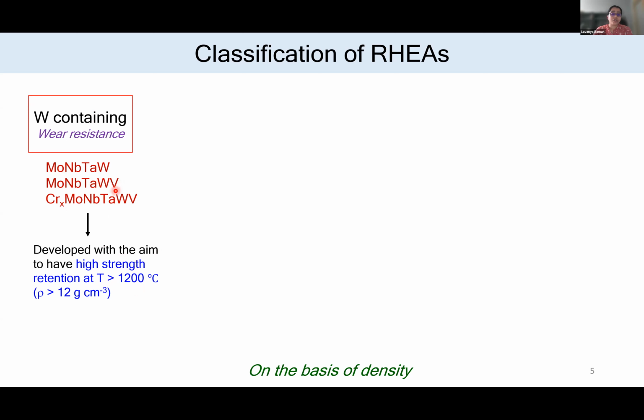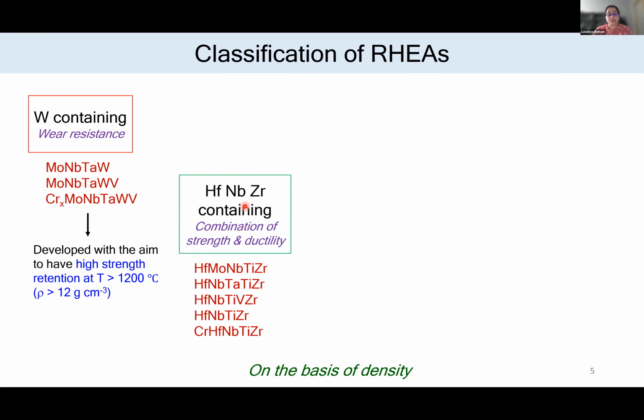But the major drawback is that they are highly dense. The density is very high. And then they modified the composition, wherein they added hafnium, niobium, and zirconium. This was mainly developed to have a combination of strength and ductility. And they were found to have a single phase, which was really good.